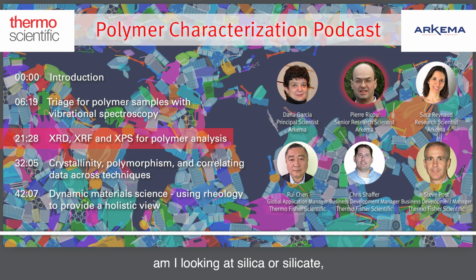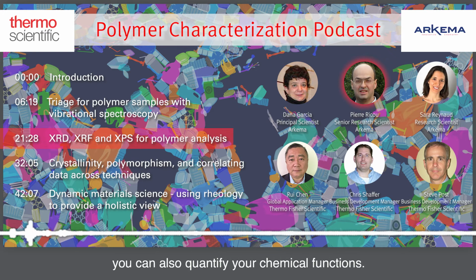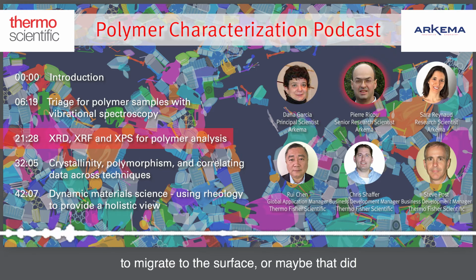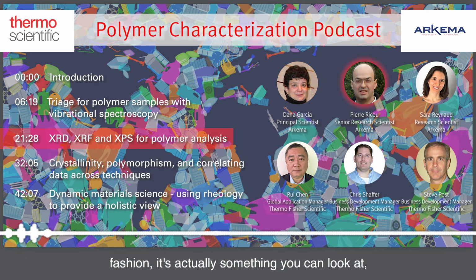Am I looking at silica or silicate, or is that a silicon PDMS type material, siloxane? So the same that you did for the element, you can also quantify your chemical functions. In the organic polymer field, if you have additives in a polymer matrix that are intended to migrate to the surface, or maybe did migrate to the surface not in a desired fashion, you can look at, evaluate, and quantify that. And I would say other techniques would be completely blind to that fact. XPS is so surface sensitive, you can get information that would be missed by other techniques.